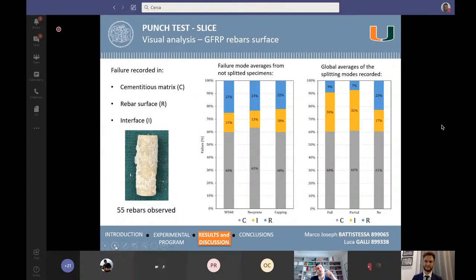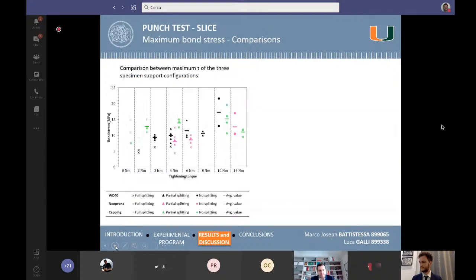Okay, let's see this graph. So we have the data of the not splitted specimens of the three different configuration systems, and also we have the global averages of the rebars analyzed and grouped as fully splitted, partially splitted, and not splitted. This graph shows similar results among the three configurations in case of not splitted samples, where we can see that a higher percentage of failure occurred at the rebar surface. In case of partially and fully splitted, this percentage decreases, while the one on the interface increases up to 30%.